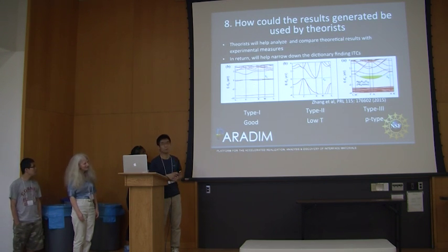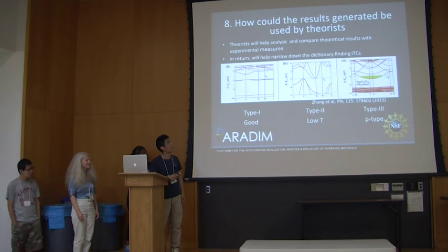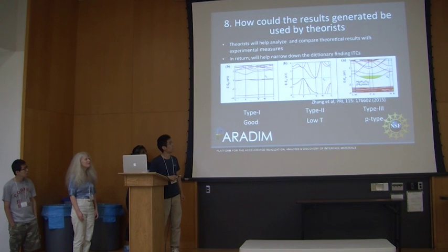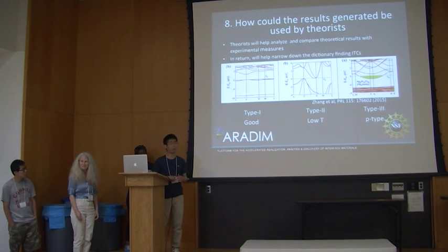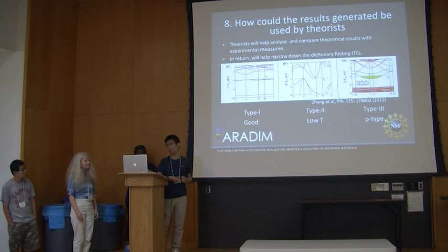The optical photon simply has no way to be absorbed. For the second type, it is promising, but we need to be careful that the phonon will play a role here for the indirect excitation. In the case of the paper that compared the silicon, I already checked the full dispersion relations, and I finally found out that the phonon will play a significant role in the indirect excitation at room temperature, which will give us the compressed silicon is actually opaque at room temperature. But at low temperature, it will work.